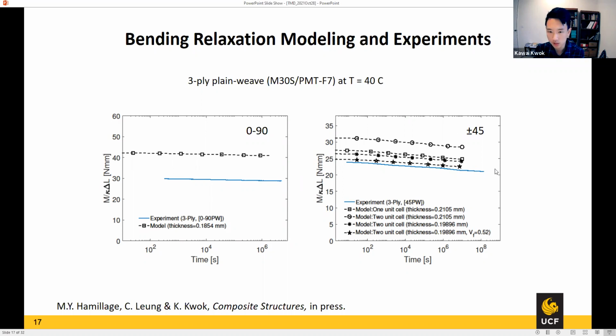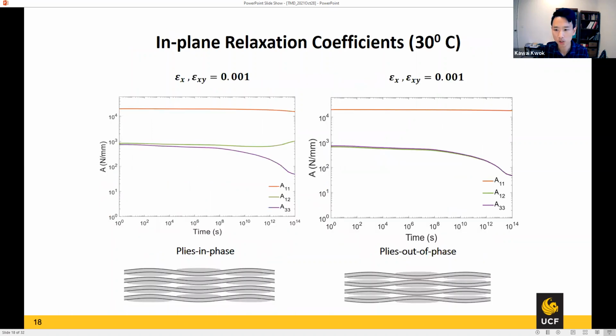And we see that the difference is less if we go to the plus or minus 45, and that makes sense because in that direction the contribution from the fibers is less. So there's going to be less contribution from the discrepancy of the fiber property that we assume. But still, there's an overprediction when compared to the experiment. But if you look at time dependence, again, they go down in a manner that is consistent with our simulation. So this is a laminate-level validation of the overall behavior.